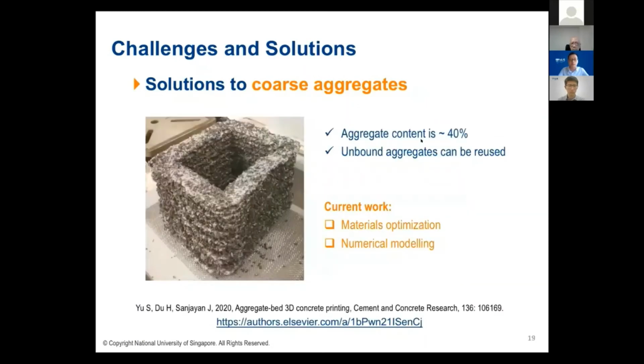For the final printed product, the aggregate content is about 40% compared to traditional 3D printed concrete. This is quite high already because traditionally there's no aggregate at all. Another good thing is the unbounded aggregate can be reused. So basically we are not wasting any materials. So my PhD student is currently working on the materials optimization and numerical modeling, as well as the automation of the aggregate spreading. If you have interest, please download this paper through this link. This was newly published, so it's free to download.